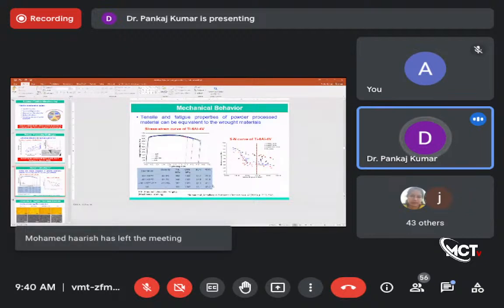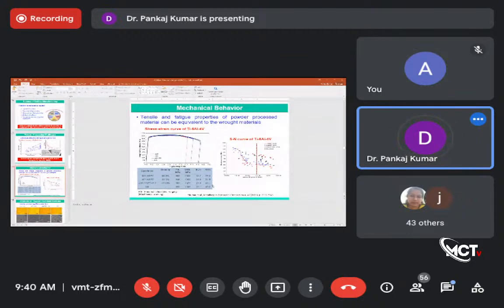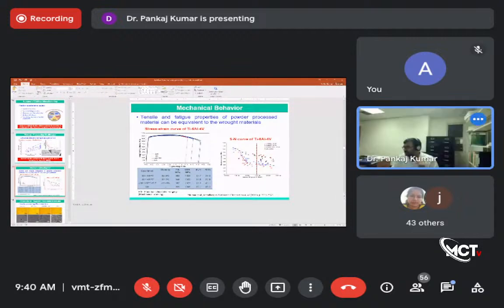So if you control the process by doing post processing methods, you should be able to get the properties that you desire. Similar to the fatigue curve, if you look at the mill annealed condition, the rod samples, and if you look at different particle sizes and the process, the black one, you see the black dot, it is actually able to show properties close to the rod product. So this is an encouraging observation, right?